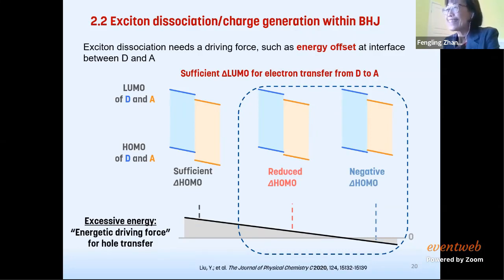I mean, the trade-off between short-circuit current and open circuit voltage is always hard to overcome. When we try to increase the open circuit voltage, we need to decrease the driving force or energy offset. If the energy offset is too small, then maybe it's not enough to separate the exciton. Like here, I show two situations on the right. The middle one has a reduced HOMO offset compared with the left one, so it's close enough that there is not a very big driving force for exciton dissociation.